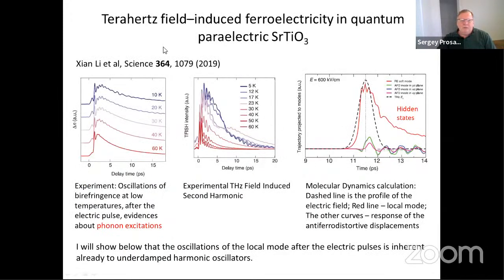Another paper, first author is Li, in Science, and these two slides are experimental. The first slide shows birefringence, and what is attractive after the pulse, after this sharp peak, there appear these oscillations of the birefringence. The authors say that phonons are excited by this pulse. Again, in our point of view, this looks different, but again, I will talk about this later.